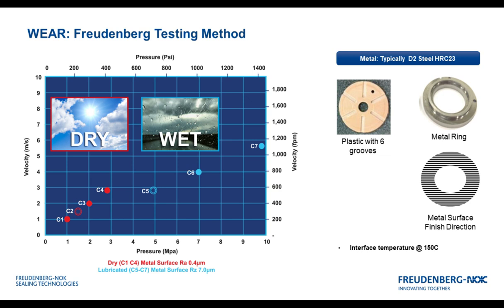This is intentional because we want this to be an aggressive test. We want the material to have to go with and cross the grain with every revolution. That's to be more aggressive to get better understanding of wear conditions. The finish we hold varies depending on the method we're testing for. So when we do dry testing, we're going to be using a surface finish of RA of 0.4, a smoother finish. When we move to the lubricated conditions, we actually become more aggressive. We want to be a more aggressive test because we have lubrication present. We move to an RZ of 7 standard.